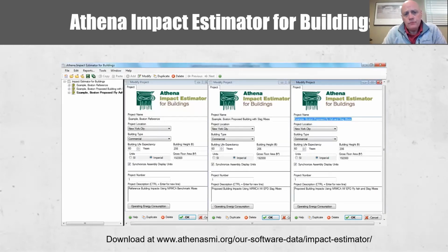So really, if you're using an LCA software, I'm using Athena only because it's free software and relatively easy to use. And keep in mind that the only materials entered in the software for this example is concrete. You would have to do this for all the building materials on the core and shell if you were doing this for LCA. But if you're establishing the carbon budget for concrete, you can do this just for the concrete on the building. So here I'm showing that I've run the software 3 times, 1 for the benchmark, and then 2 for different scenarios, one using all slag for cement replacement, and the other one using a slag and fly ash combination.